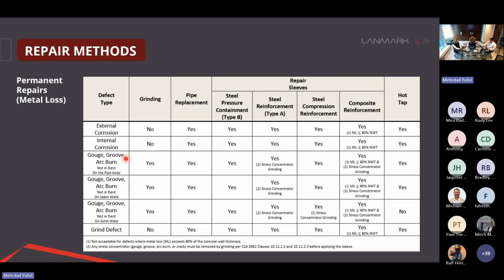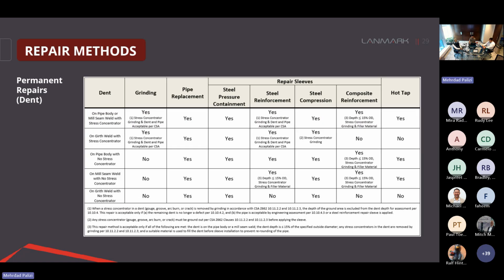For the rest of the metal loss issues like gouges, grooves, or arc burns, we also have the option for grinding, but after grinding, we should make sure that based on the B31G modified formulation, we have enough wall thickness remaining. We can also apply sleeves, but in the case of steel reinforcement type A and composite reinforcement, we should grind the stress concentrator. This is another part of that table. This part is related to dents. Any other questions so far?